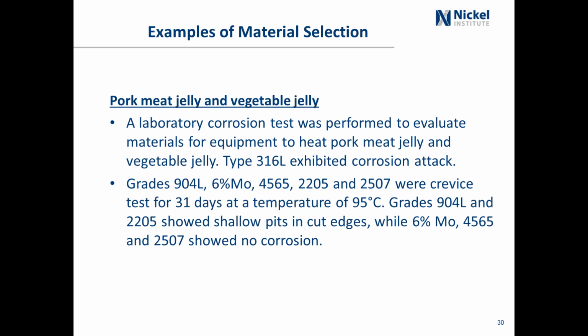They were all crevice tested for 31 days at a temperature of 95 degrees. 904L and 2205 showed shallow pits on cut edges, while the 6 moly, the 4565 and 2507 showed no corrosion. That's because in the previous table I showed you that 904L and 2205 have about the same PREN number, which is about 34 to 35. These other alloys, the 6 moly, the 4565 and 2507, have a PREN that's greater than 40, probably somewhere between 40 and 42, and they're resistant to the salt in this application.